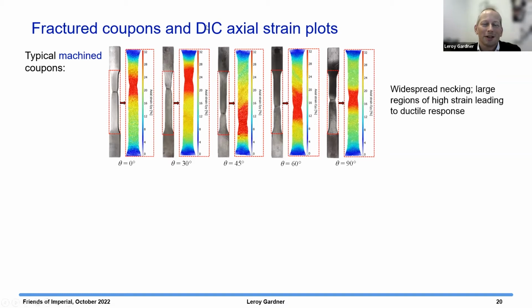So we used a method of measurement called DIC. So it's not Diploma of Imperial College, this one. It's digital image correlation. And it's a sort of non-contact measurement method, which enables you to get much more information than traditional measurement techniques. But what these are showing you, the first set of diagrams here are for the machined coupons at different angles. We've got a couple of intermediate angles that we looked at as well.